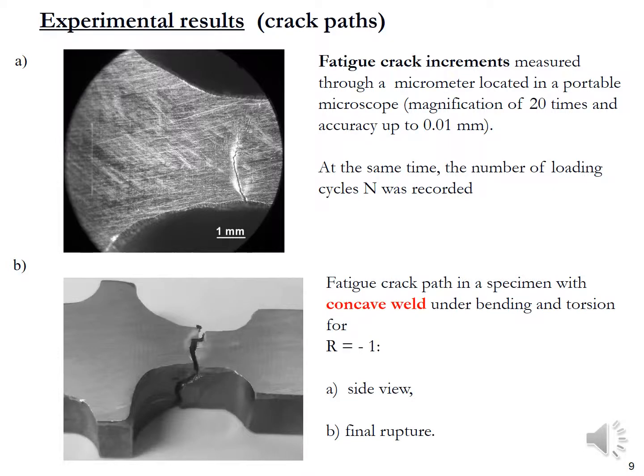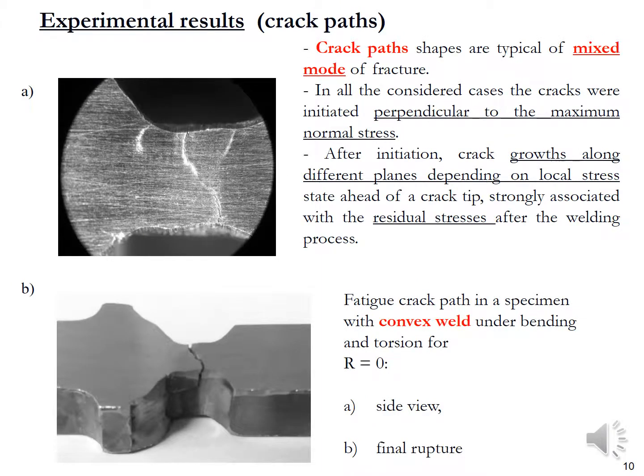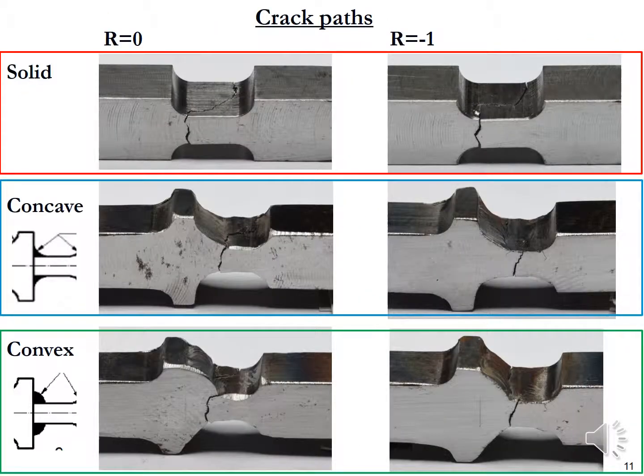The experimental crack path has been observed and measured through a microscope equipped with a micrometer. The crack paths are typical of mixed mode fracture, starting perpendicularly to the maximum principal stress and then growing along planes whose orientation is strongly dependent on local stress ahead of the crack tip. The different crack paths obtained for all the examined cases and for the two assumed stress ratios are summarized here. In all cases, the crack starts from the weld toe but propagates differently depending on the weld geometry.